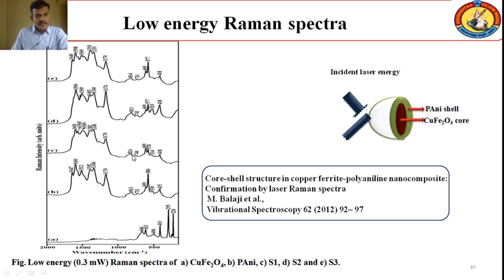In the addition of polyaniline with the copper ferrite, which is low concentration of polyaniline in S1, it shows a minimum peak behavior of copper ferrite here. Similarly, the polyaniline characteristic behavior is also present in this S1. So when you increase the polyaniline concentration, the polyaniline characteristic behavior is presented along with the minute characteristic behavior of ferrite element.